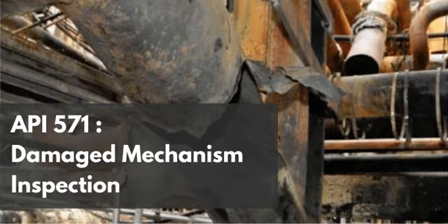Right, it's a great distinction to make. When we say uniform thinning, we mean that within a specific isolated area of the piping or the vessel, so perhaps a specific elbow, a reducer, or a particular run of pipe coming off a heat exchanger, the wall thickness is reducing relatively evenly across that specific zone. Okay, so just in that one elbow, the whole wall is washing away. Exactly. The surface within that zone might look relatively smooth, but the entire wall is getting thinner. It's not a single pinpoint hole, like pitting, but rather a broad, sweeping area of metal loss that is strictly confined to a particular region of the system. While the pipe, like 10 feet upstream, might be perfectly fine. Precisely. It's untouched. Okay, that makes sense. It's a localized zone of uniform washout.